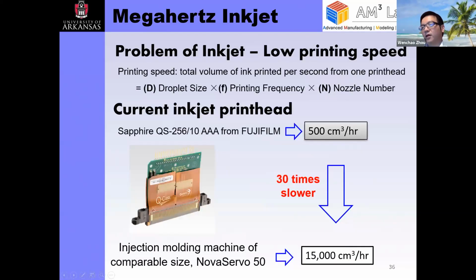One of the things about inkjet printing speed is that it is controlled by three factors. The first one is droplet size, how large the droplet is. The second is printing frequency, and the third is the number of nozzles that you have. For droplet size, you can't really do too much to control that, because one of the advantages of inkjet is the resolution. For example, for a 600 dpi resolution, you are talking about a 50 micron droplet size. With larger droplet size, the resolution will go down. So if you don't want to sacrifice your resolution, you need to maintain similar droplet size.